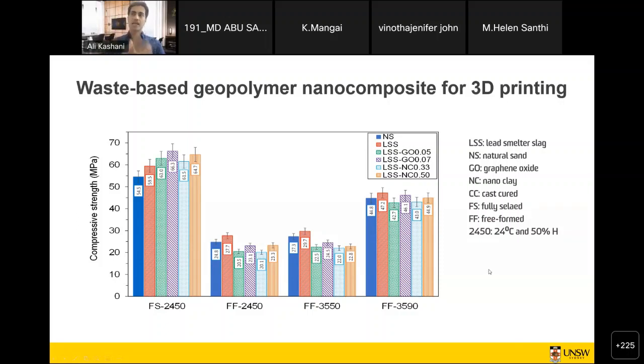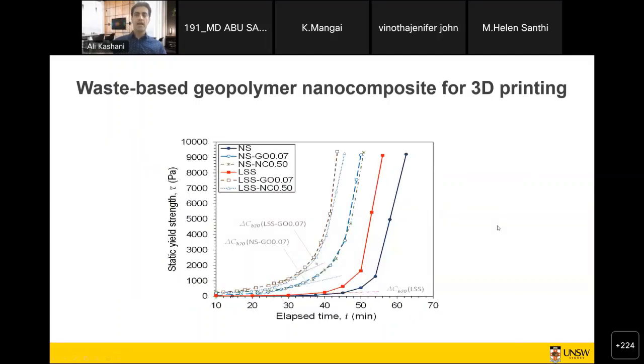So keeping the water in the first 24 hours inside the printed sample is vital for strength development, and also if you use any other additives such as these nanomaterials to help with the strength development. So you may ask why we are using these nanomaterials. What's the purpose of that? Geopolymer material normally is not that thixotropic.